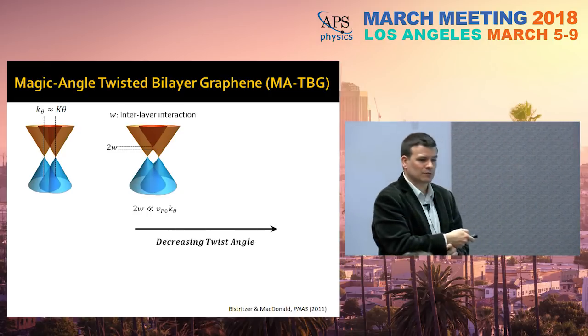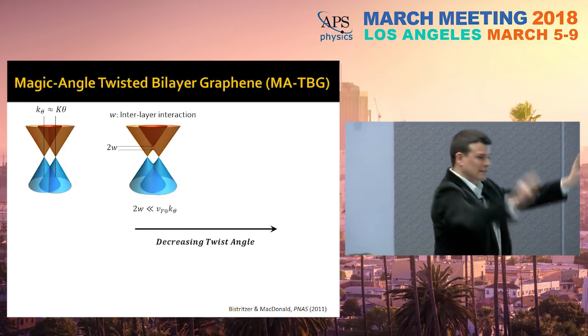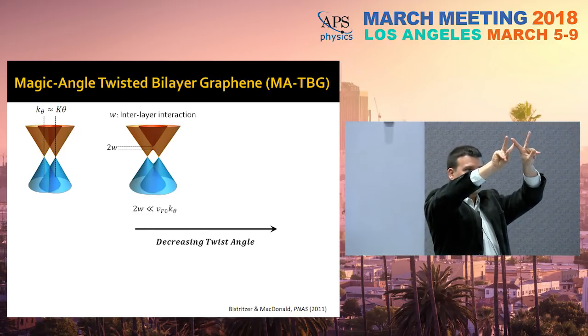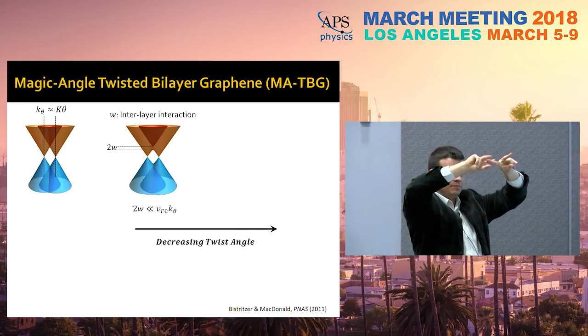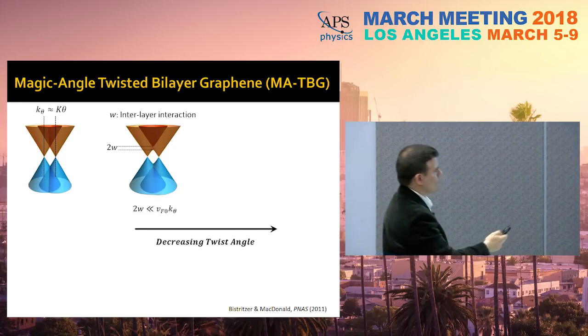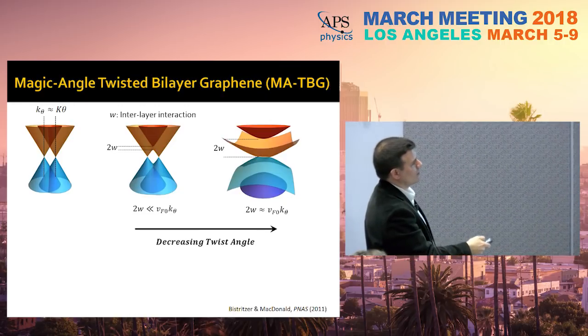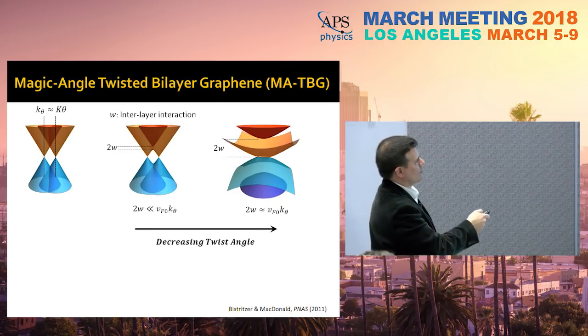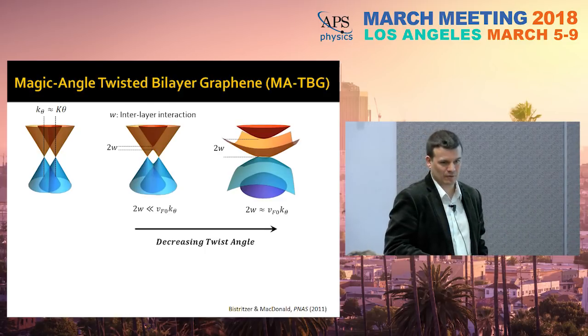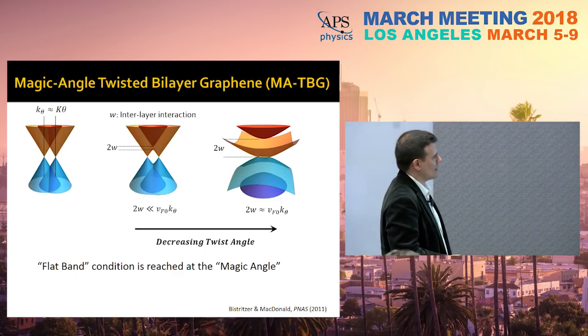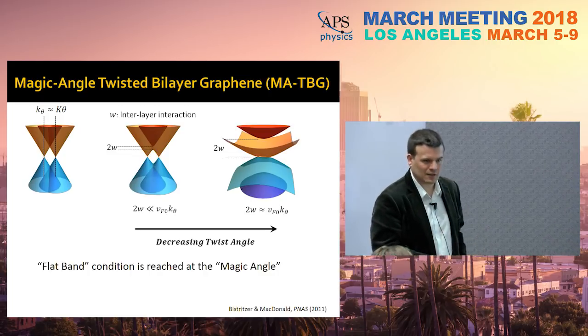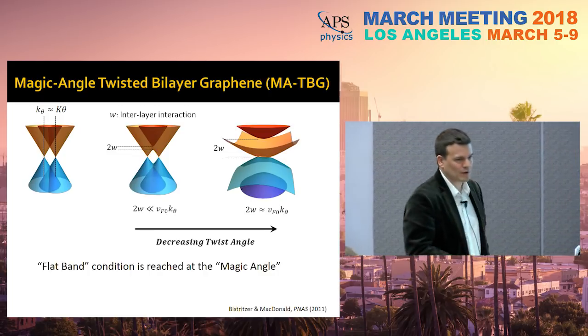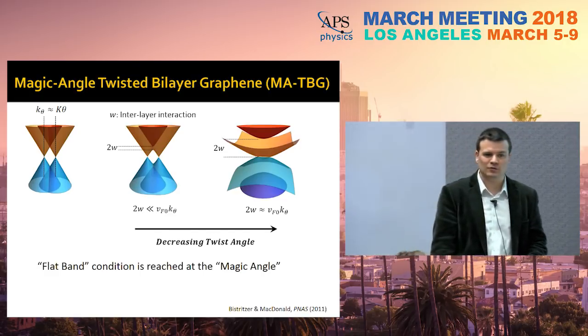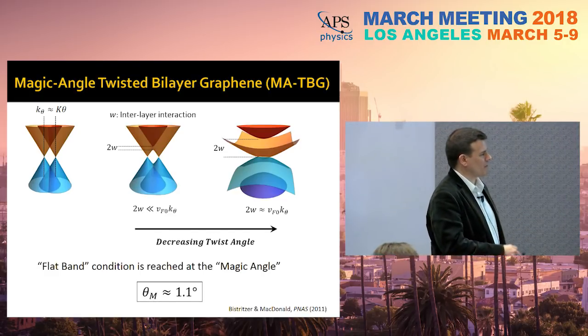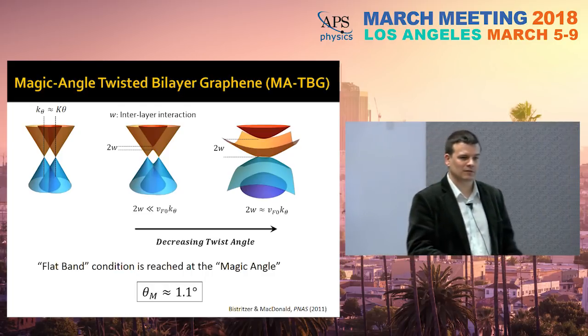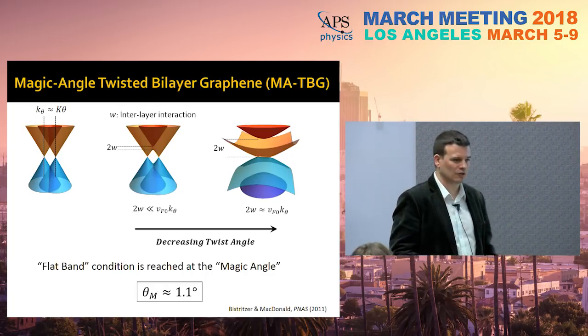However, if I now decrease the twist angle, you can imagine that as I take these two Dirac cones, which are crossing here, and I make them closer and closer, this opening of a gap flattens the bottom band such that you realize a situation like this. When your interlayer coupling is very similar to that crossing point, you have a flat band now. This flat band condition is reached at the so-called magic angle, a term coined by Bistritzer and MacDonald. It depends on what the interlayer coupling is between these two sheets. So for graphene on top of graphene, this magic angle happens to be 1.1 degrees. At that value, you reach a flat band condition.